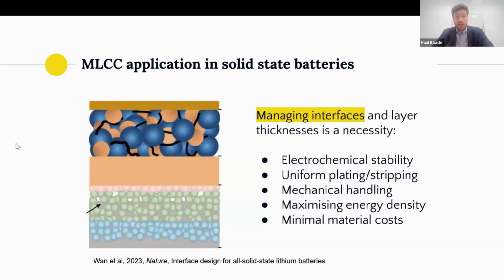Now, last but not least, I also promised I'll share some insights on how we think about solid-state batteries. They are a beast of their own. They have multiple tricky challenges. But to sum it up, I believe that solid-state batteries and scaling solid-state batteries in particular is about managing interfaces between different kinds of materials and the corresponding layer thicknesses. And why is that the case? Well, essentially, it's about electrochemical stability. Where in your layup do you have actually the material that is stable when in contact with lithium metal? Do you have the right interface to enable uniform plating and stripping towards lithium metal?